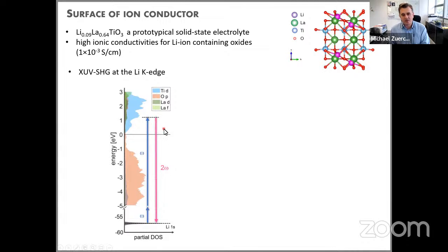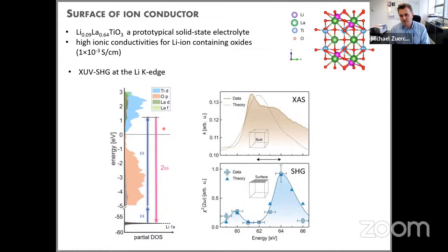This is what we observed, comparing bulk and surface measurements. The XAS bulk measurements were done at the Advanced Light Source at Berkeley on the same sample. What we see nicely is the lithium K edge, which is what you find in many textbooks. We can also use our DFT methods to predict and estimate the shape of this edge. So that is essentially the bulk response of the system.